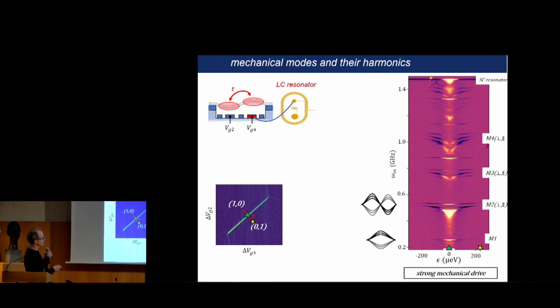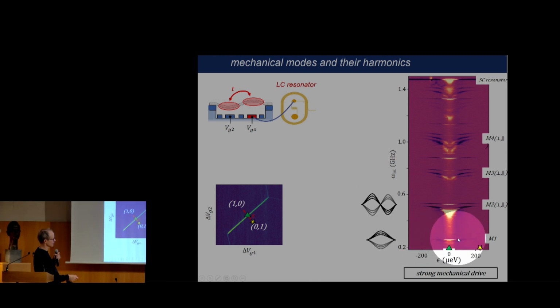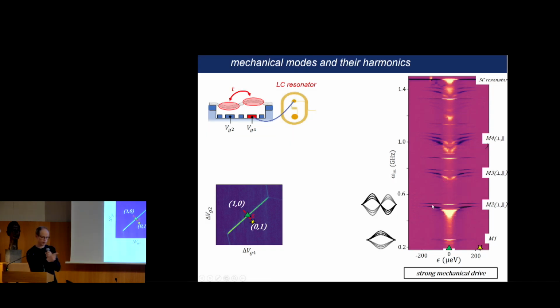We use the superconducting resonator to measure the mechanical vibrations. And in fact, when we drive the system very strongly, we can detect almost all the mechanical modes. And this is what is shown here. So here we have the fundamental mode of the vibration, where I show you the shape of the eigenstate. Then here we have the next mode, with the eigenshape shown here, where you have one node. Okay, and then you have two lines because you have the two polarizations, parallel and perpendicular.